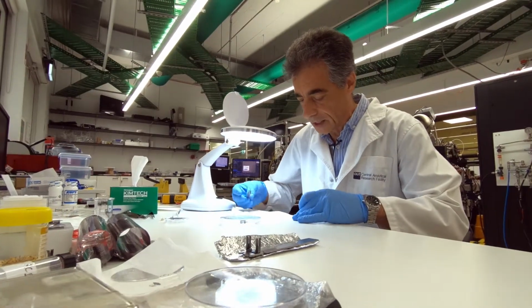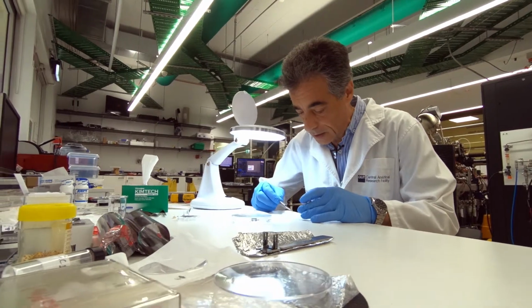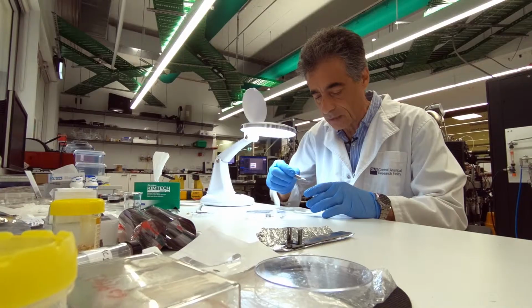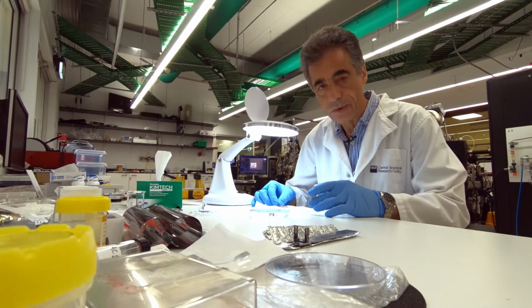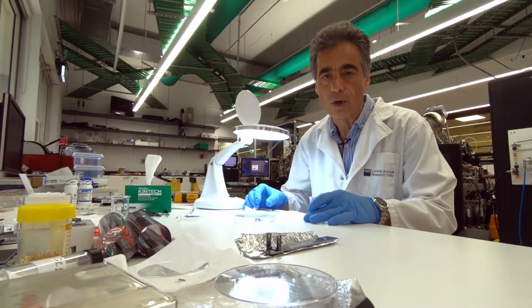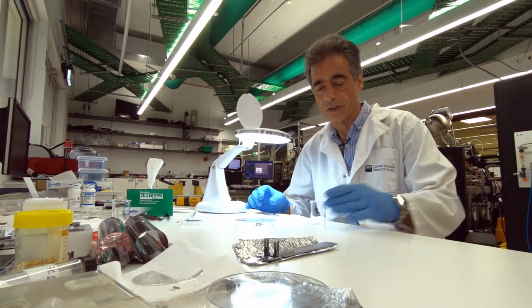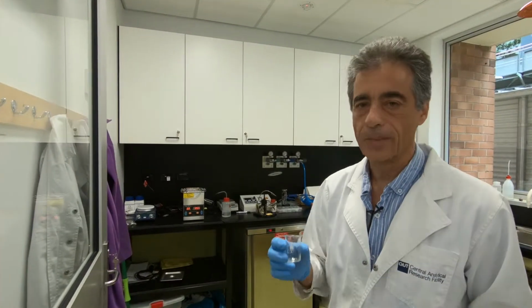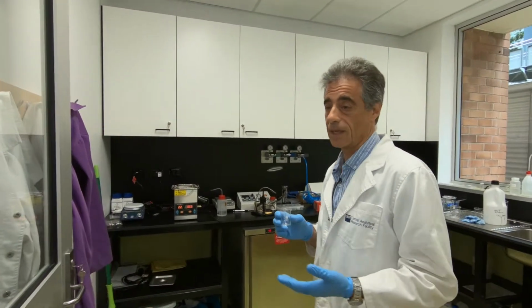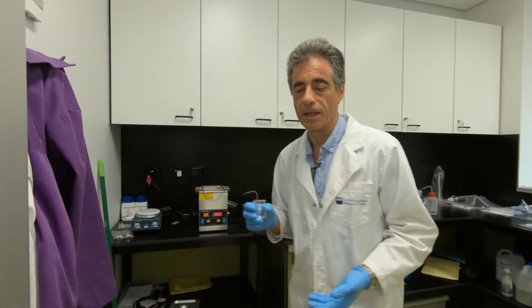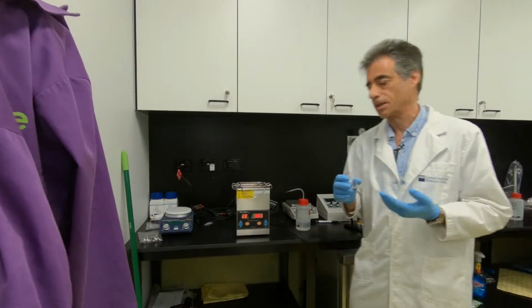Now let us take a piece of silicon carbide. This is a special wafer that we buy and we cut. We put it into the beaker and we go and wash it in the ultrasound station. And now we're going to wash the sample by using some solvents and ultrasound in order to make sure that the sample is really very clean before entering the vacuum.